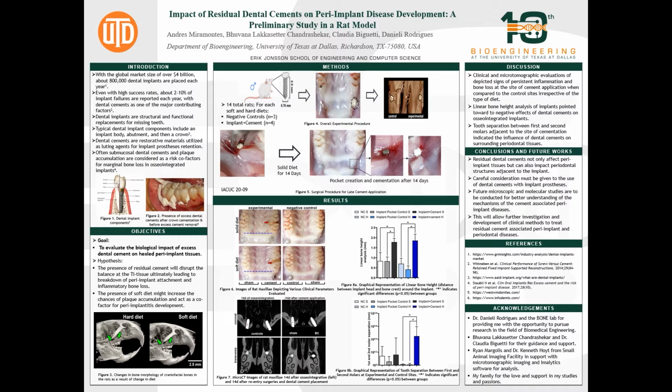In Figure 6, we can see under the experimental clinical evaluation that the implant is exposed, especially for the soft diet group, and that both groups are experiencing redness, plaque accumulation around the cemented area, and inflammatory bone loss. The microtomographic scans in Figure 7 give us a better look into areas where we experience bone loss. 14 days after the cement application, we can see how there is bone loss at the cement application site on the right when compared to the pocket control site on the left.